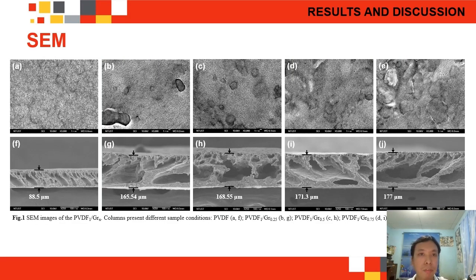SEM. From figures A to E, it is observed that the addition of graphene transformed the porous surface of PVDF into a fish scale-like structure composed of stacked graphene. Also, for figures F to J, originally featuring asymmetric large pore structures, it is transformed into continuous giant pore structures with the addition of graphene. The thickness increased with the amount of graphene added, increasing from the original 88.5 micrometers of PVDF to 177 micrometers in PVDF1 graphene 1. The formation of pores can impact the piezoelectric response of the membrane as it influences the deformation and strain of the membrane during its operational processes.